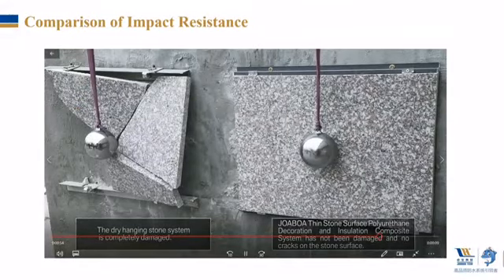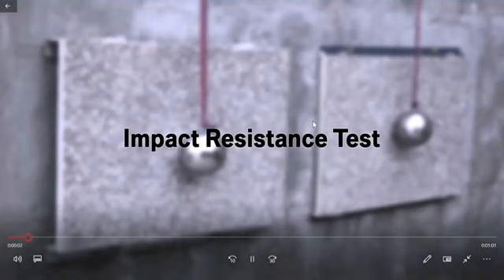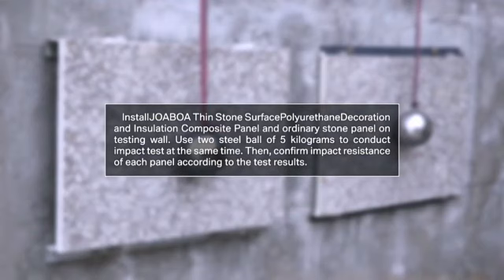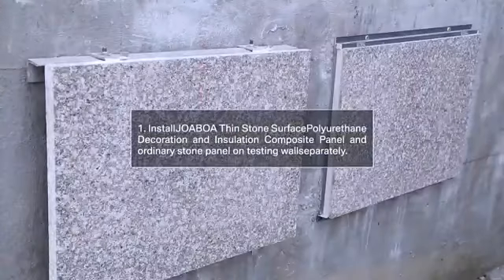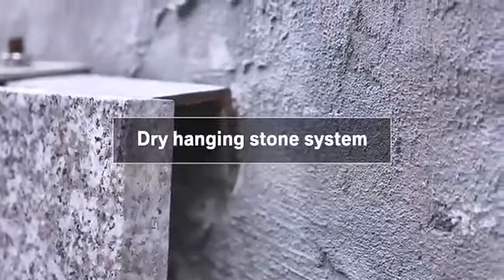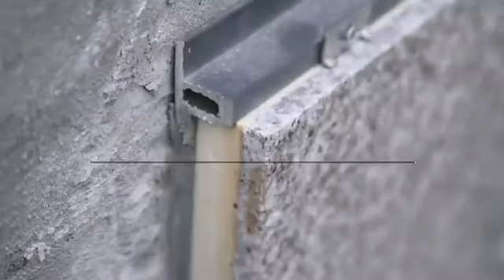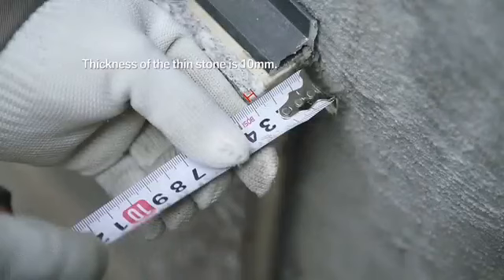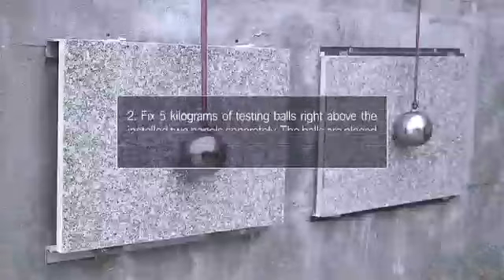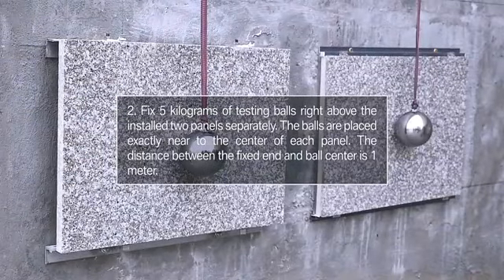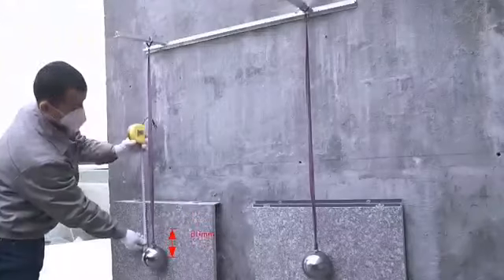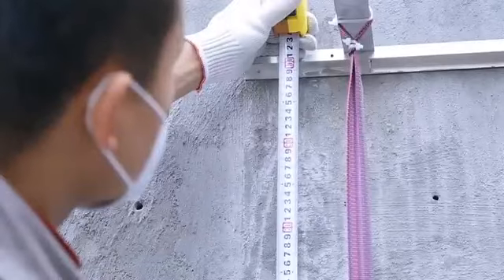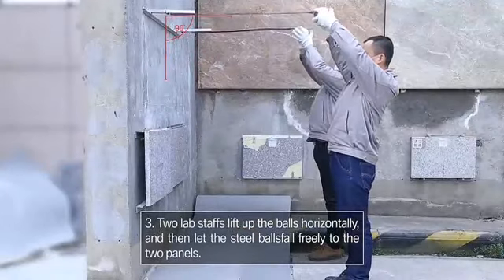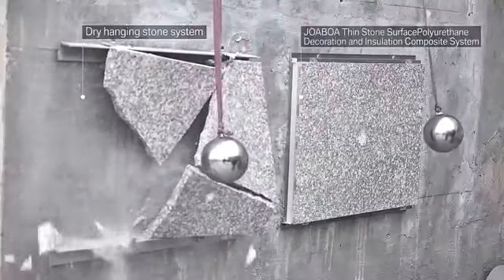And also here, I offer a test we conducted to check the impact resistance of our stone surface integration system. So we'll use a steel ball to hit both of these two systems. The thickness of stone used in Jobatech's integration system on the right side is only 10 mm, but for the traditional one, as you may see, is 25 mm thickness. And then we will use a 5 kilogram metal ball to hit both of these two systems. So lift the balls horizontally, then hit them on the surface of the panels.